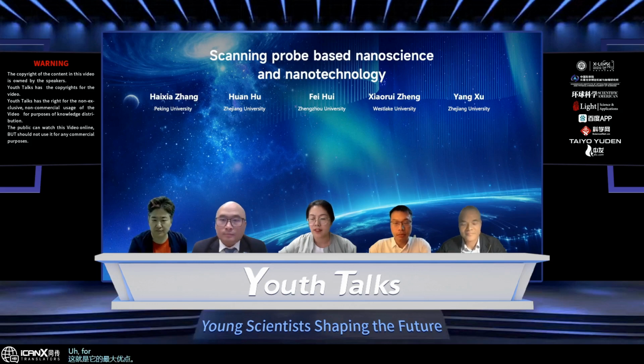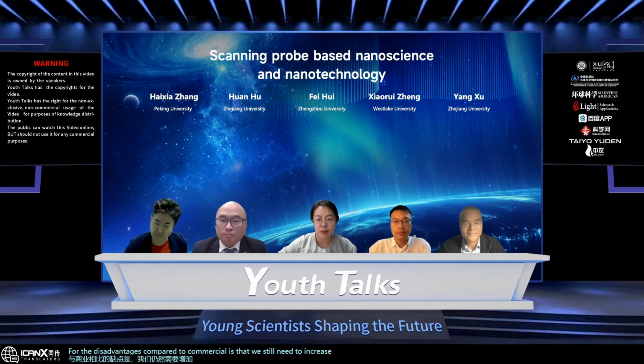For the disadvantages compared to commercial tips, we still need to increase focus on reproducibility, because the yield of the graphene coated tip is still low, and so we need to develop a scalable methodology to get the graphene coated tip for commercialization. Yeah.